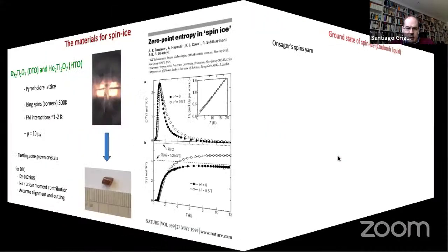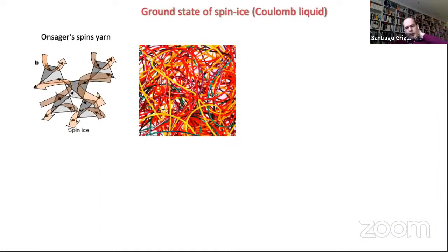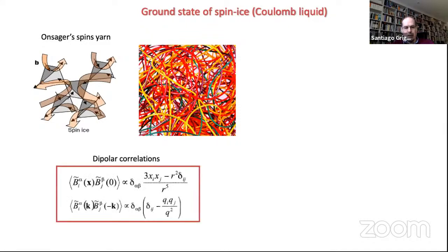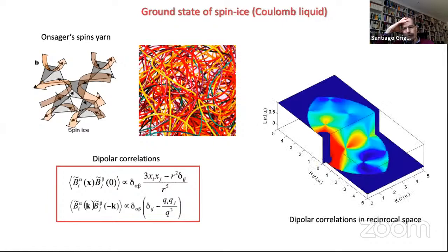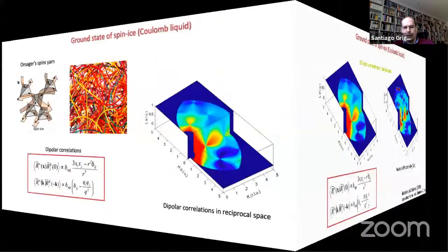Okay. So going back to this idea of Onsager, this idea that you can think of the system as some sort of a yarn where you have all these threads or these strings going around the system. It's very good for realizing that this means that the system might have a very high entropy, but it's not completely disordered. So you expect to find correlations in the ground state. And when you do the calculation, what you find is that what you get are dipolar correlations. So one way of checking whether the ground state you're looking at is the one you expect is just to, okay, this is the calculation, what you will get from these correlations in reciprocal space. And now you can do a neutron experiment and check for these dipolar correlations.